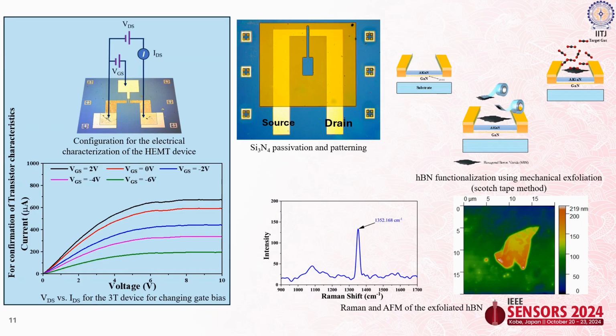Just to verify, in some of the devices we first even made a gate and checked with different gate biases. It gives transistor-like characteristics. But for our work, we just went with this source and drain, and we passivated all the area using silicon nitride, deposited and patterned. Then the gate area that you see in the central part, we are using for functionalization. We are functionalizing with hexagonal boron nitride using the Scotch tape method on the gate surface. We confirmed it with Raman and took the AFM of it, and the thickness that we are getting is not very thin like we expected, but it is in the range of around 200 nanometers.